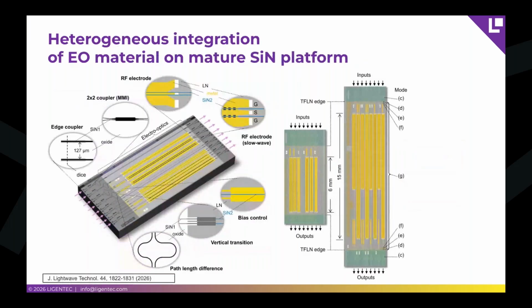So here we see the integration example of nitride plus lithium niobate and the different components that we're using. We start with the edge couplers on the left hand side, then go to the 2x2 MMIs, and then these split and go through the RF electrode. And on the bottom we have path length difference in the Mach-Zehnder interferometer, and go to a vertical transition from the nitride into the hybrid mode consisting of nitride plus lithium niobate, and then also have a bias control integrated on the lithium niobate chip.